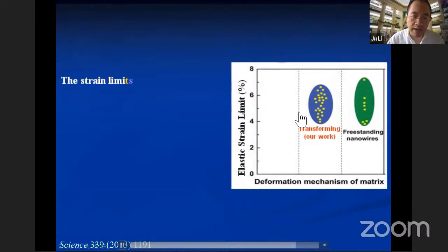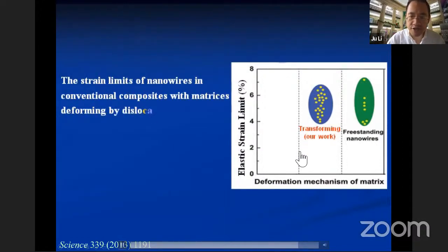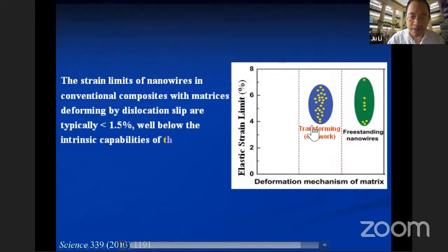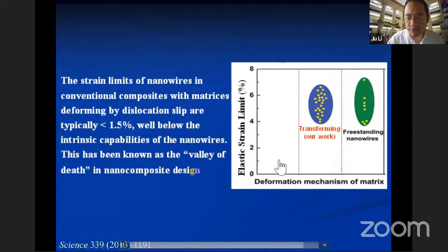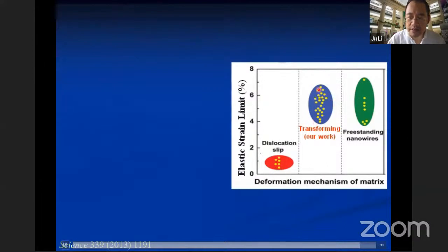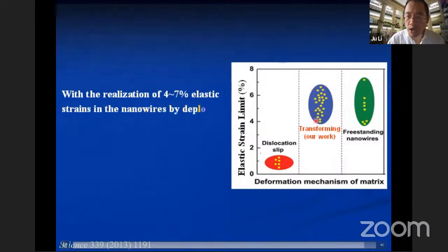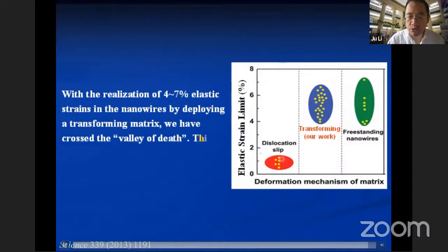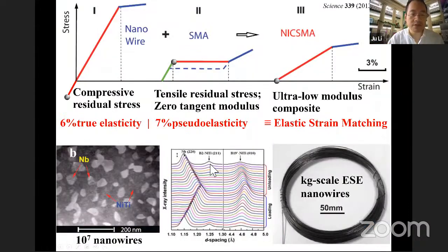Because if we just tune the alloy composition a little bit, just change the composition a little bit to have even just a little bit of dislocation slip, boom, we see the elastic strain limit of the niobium drops from 6% by a factor of 4 to 1.5%. So the key idea here is that to preserve the huge true elasticity of the body center cubic niobium, it must be matched by this phase transformation pseudo elasticity.